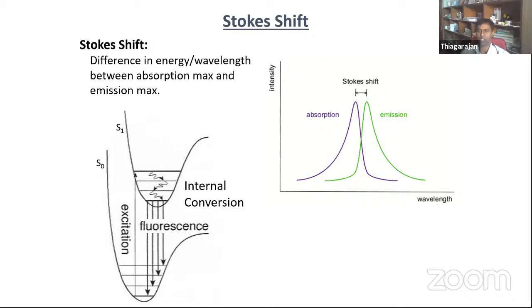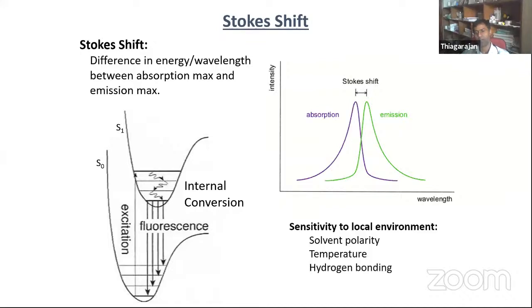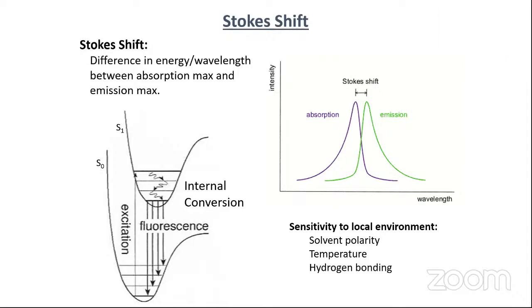Large Stokes shift means the absorption and emission should be separated far away, not in a very close line. And the Stokes shift depends on the solvent polarity, the temperature and the hydrogen bond. For example, if we have a donor and acceptor, and I use methanol or water, the solvent hydrogen bonding interacts with the probe and changes its Stokes shift also. The temperature also plays a role, because temperature changes the rigidity of the molecule, and then it changes the Stokes shift also.